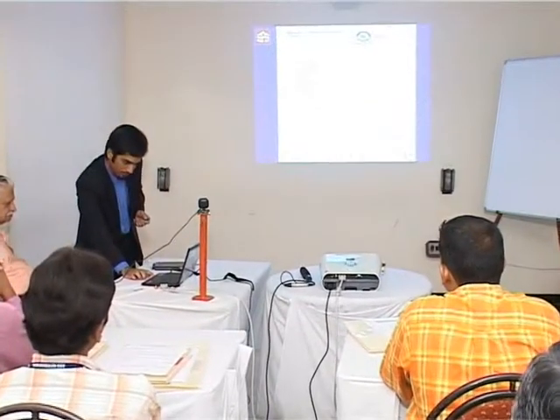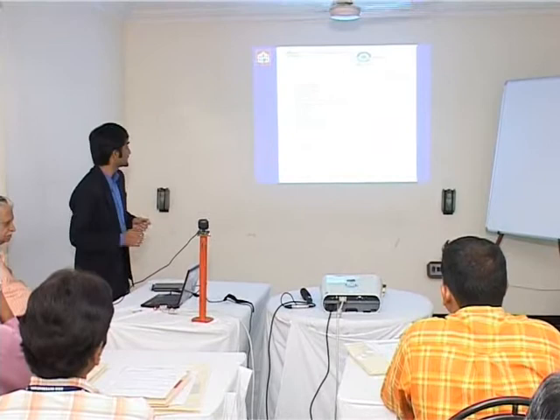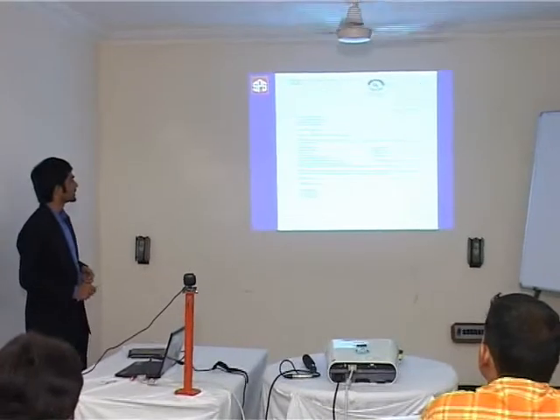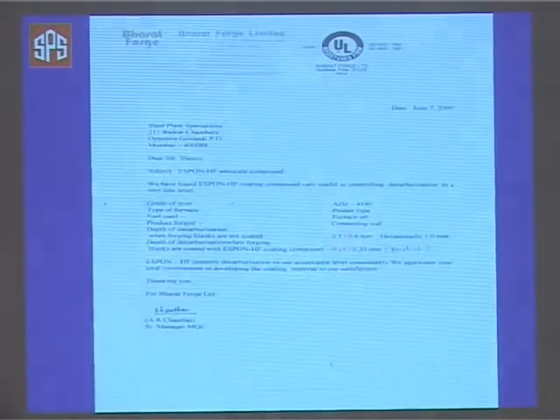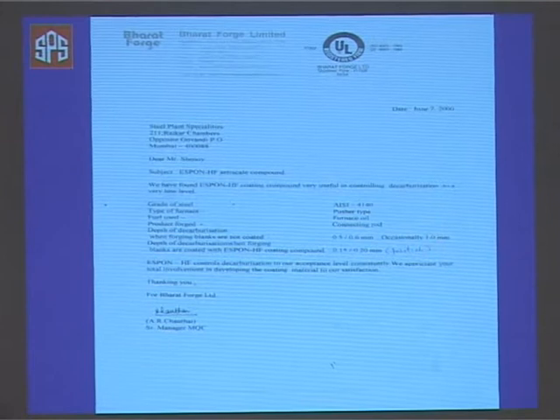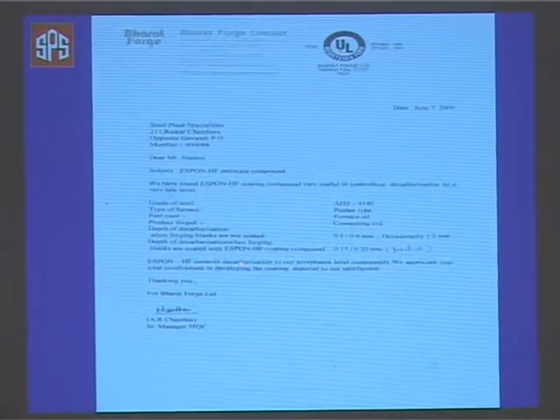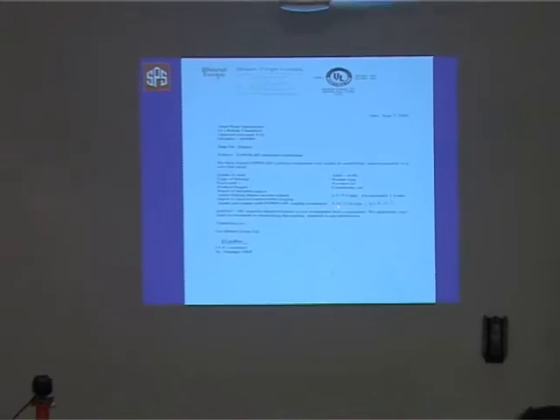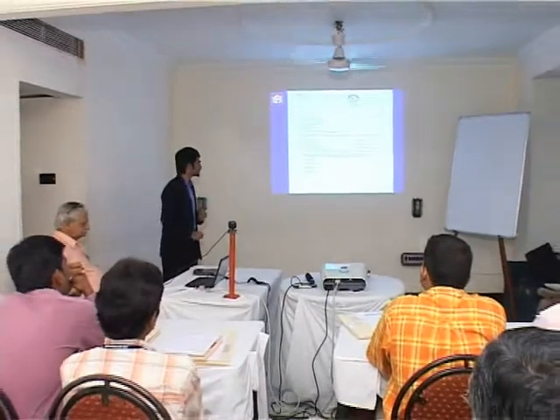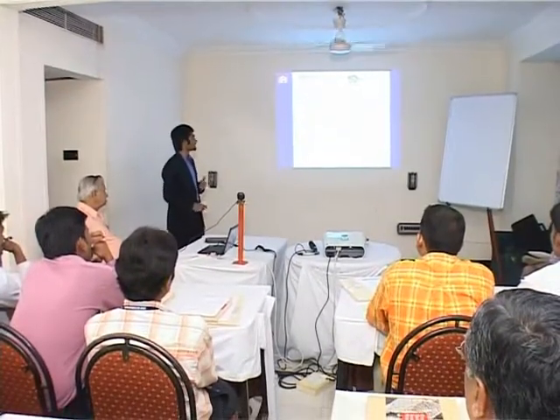This is again a pictorial representation, the same image before. This is at Bharat Forge Limited where they wanted to prevent decarburization on the billets. What is mentioned over here, let me just read out to you. The depth of decarburization when forging blanks are not coated is 0.5 to 0.6 mm, occasionally 1 mm. And the depth of decarburization when forging blanks are coated with an anti-scale compound is 0.15 to 0.20 mm, and that too partial. So of course they have certified that it controls decarburization up to their accepted level.